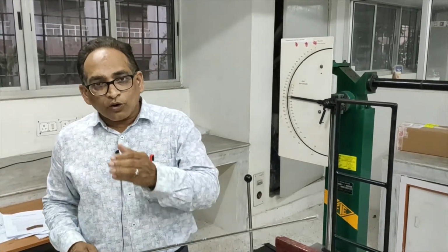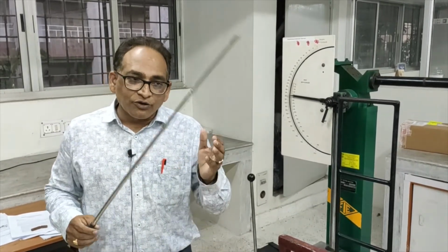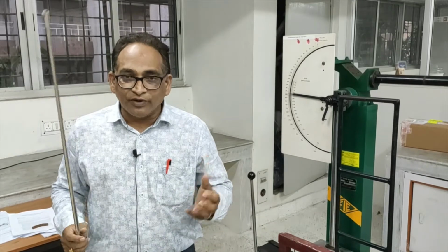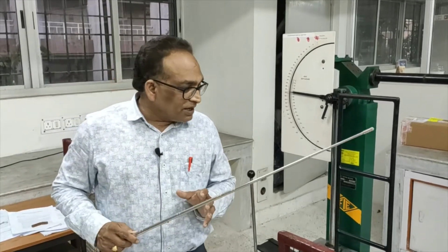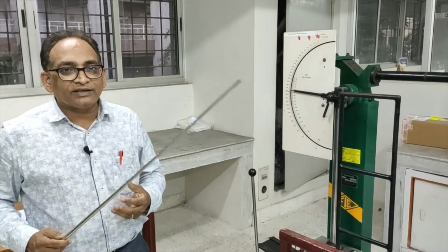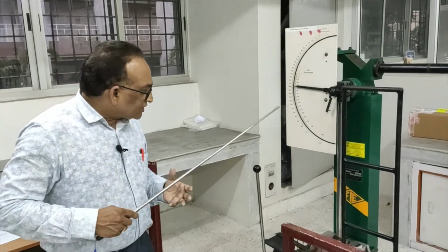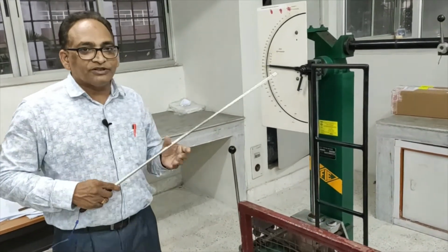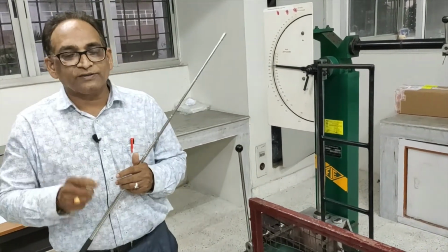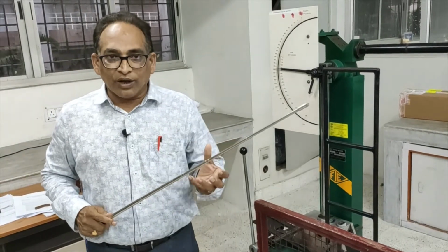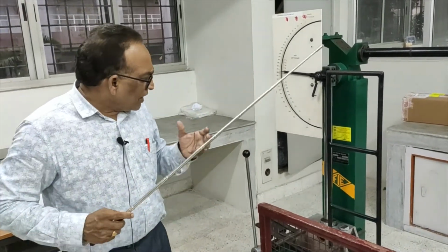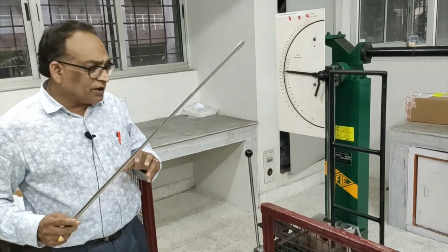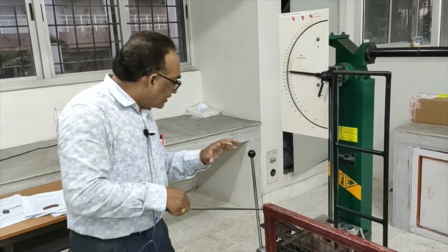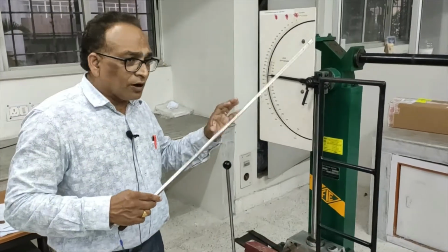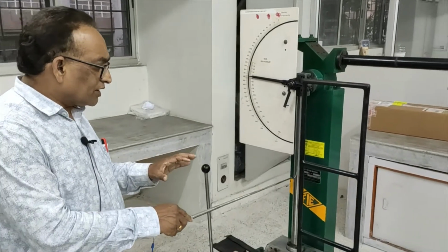Without marking with that diamond pen, if you try to break the glass, it becomes very, very difficult. In a similar way, to break the materials easily, for the specimens of this impact testing machine, we create some notches, a V notch and a U notch. And depending on the U notch and V notch, we can find out the amount of energy which is absorbed upon striking by this hammer.